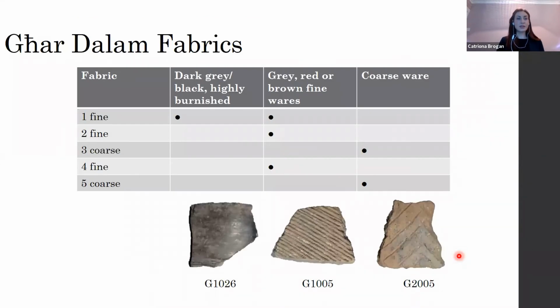So we decided that it might be useful to try and link the internal fabrics with the external appearance. Generally, with the Għar Dalam fabrics, the three main styles of pottery that you find are this very highly burnished black fine ware, which often has geometric designs on it. And what we find is that it was only associated with one fabric, which was the fine ware. And it was also the most common fabric that we have.